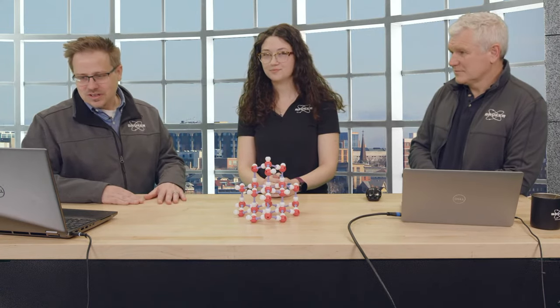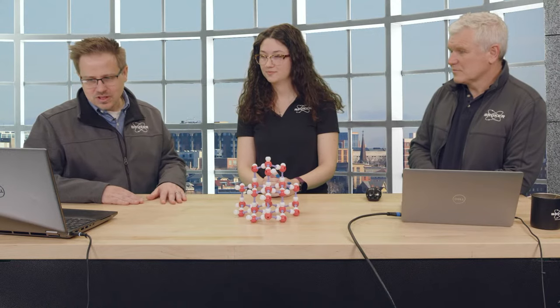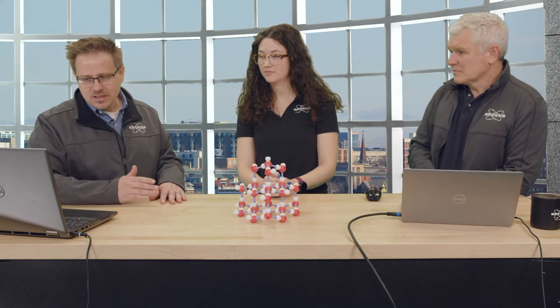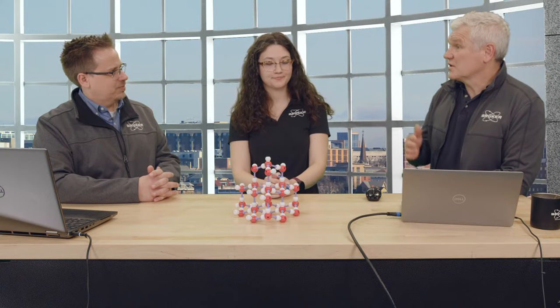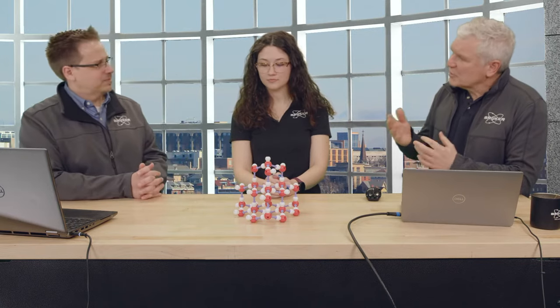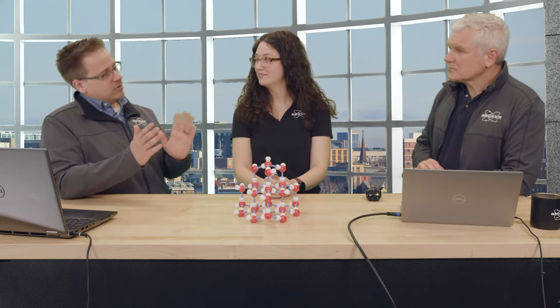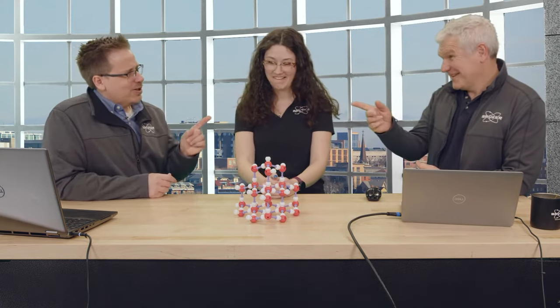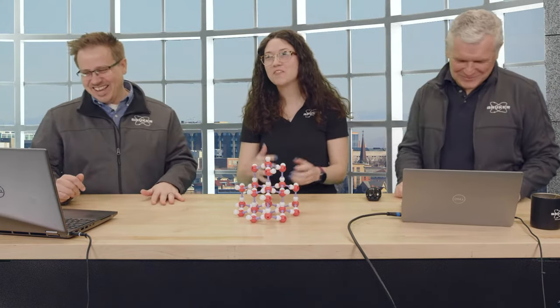All right, next question, also from Kuldeep. What is the difference between commensurate and incommensurate? Let's say we had a modulation, and our q vector would be 0.25. That's a quarter, so that's commensurate. Then you can probably get away with just treating this as a superstructure. If it's something that doesn't divide evenly into one, then it's incommensurate, like 0.291 or 0.3. But 0.3333333 is pretty darn close. It's not quite a third, right? You could probably get away with a supercell on that.